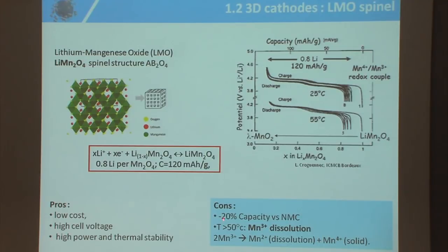But here again, you have minus 20% of capacity versus NMC. You are limited to 120 milliampere-hour per gram. And when the temperature reaches 55 degrees Celsius, you start to have a manganese dissolution by dismutation. So this is a problem. You have to manage the heat of a battery.